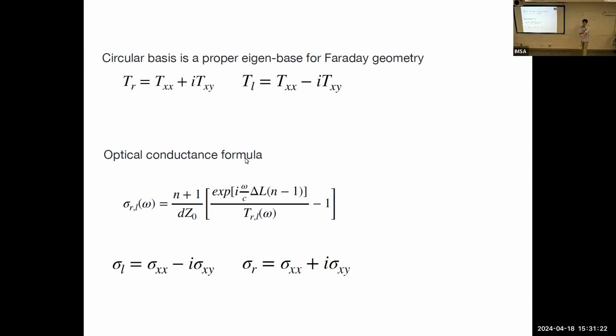I was wondering if there's some change in dielectric constant, etc. How would that affect it? Oh yeah, it's important that you don't have any sharp features in your spectra in the region where you're doing this. Actually, we have a phonon in this material, but it's at 1.6 terahertz or something, which is not in the low frequency part. So it doesn't really affect it. It's flat until then.